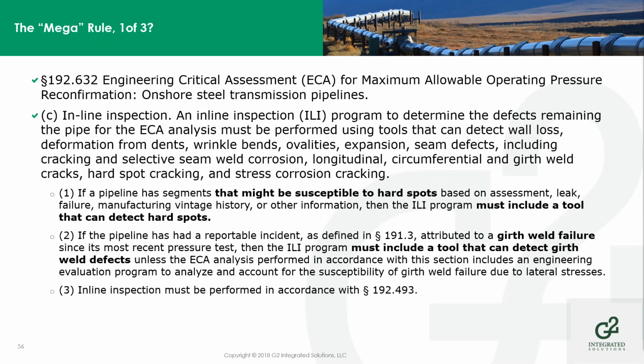For an inline inspection program to determine the defects, the pipeline segments that might be susceptible to hard spots must include a tool that can detect hard spots. If the pipeline has a reportable incident as defined in 191.3 attributed to a girth weld failure, then the tool has to be able to detect girth weld defects. And inline inspection must be performed in accordance with 192.493.